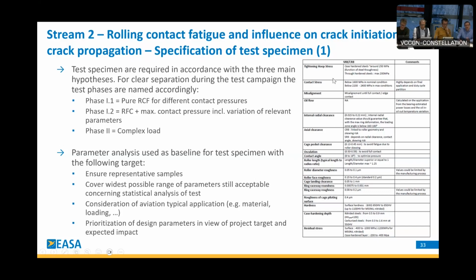And we see that we have already here a number of parameters that are typically used for the design of such bearings in an aviation environment. And we needed to look at which ones are the most prominent, the most important factors for the next steps for the testing. For example, we have the contact stress, where a certain range is, I would say, best known in the industry. Or we have residual stresses that are also typically applied.